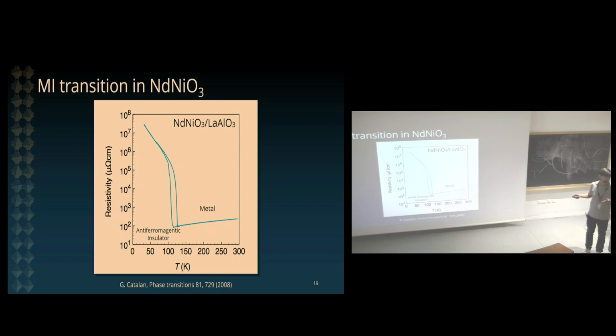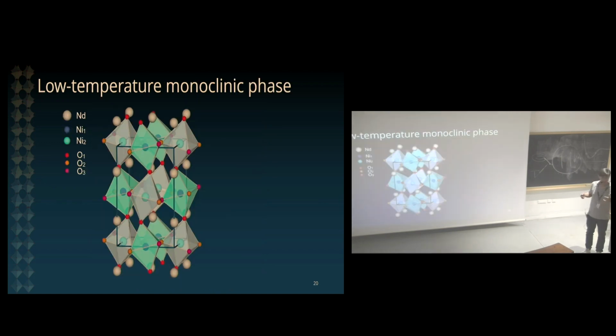You're probably all familiar with the physics of the nickelates. Let me just remind you that these guys have a very sharp metal to insulator transition, with a temperature of this transition that strongly depends on the mechanical boundary condition. And in the insulating state, we also have a very interesting antiferromagnetic order. So associated with this electronic transition, there is a structural distortion. That's described by a breathing mode. So we go from an orthorhombic to a monoclinic phase.